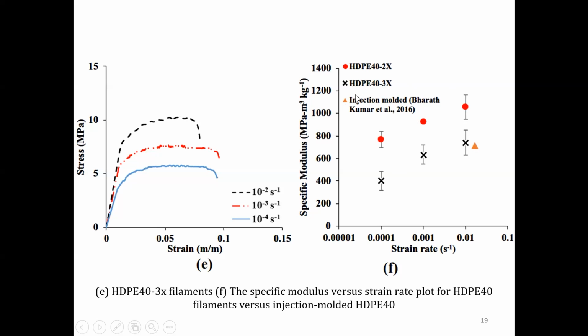So what this says is, these lines, cross marks are 40%. This is also 40%. Okay, injection molded one. Same composition, same material, same temperature set in injection molding as well as for extrusion. So these two are wires or filaments. This is 3 times extruded, 40% by weight of cenospheres infused in HDPE. This is 2 times extruded, 40% weight fraction of fly ash cenospheres infused in HDPE.